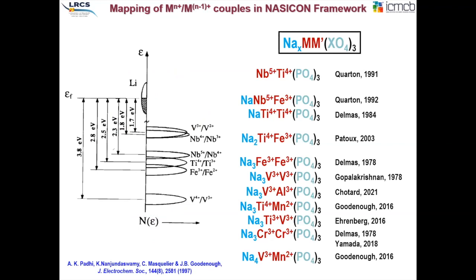We can play with different redox couples that operate on these materials. Different redox couples will build electrodes that will function at different voltage versus sodium. This is very useful for monitoring the voltage you will obtain, and also to create, as has been done by some companies in the US, aqueous sodium batteries based on NASICON electrodes.